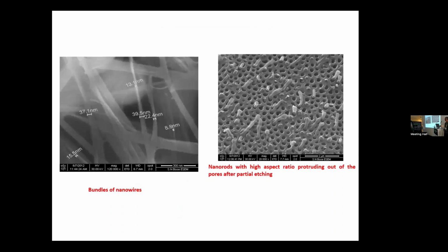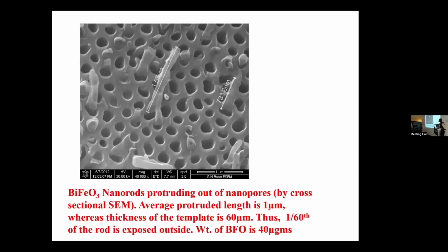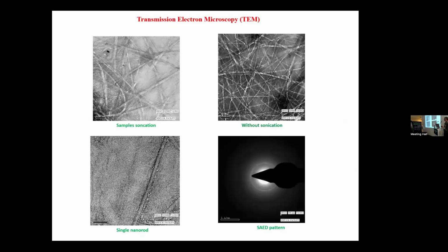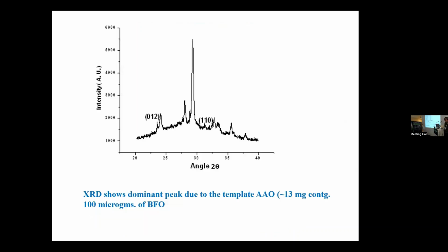And we ultimately got these nanorods. See, this is the FESEM image, and the cross-sectional FESEM shows the protruded things within the pores. These are the nanorods of bismuth ferrite, around 1 micron in length, deep in the nanopores. So one-sixtieth of the length is exposed outside, and this is the portion of interest to us. This is the usual transmission electron microscopy, and selected area electron diffraction shows that it is of polycrystalline nature. This is the X-ray diffractogram. This is mostly anodized alumina, but you see a small characteristic peak of 110 of bismuth ferrite, which shows its presence in the material.